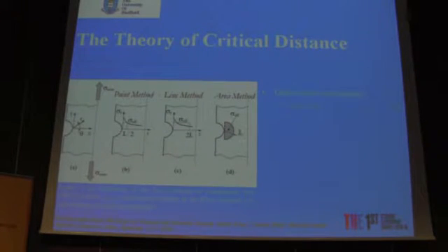It is well recognized that the theory of critical distance is the most effective tool which can be used by structural engineers to take into account the notch effect. If we pay attention to the model with static loading, we just use the simple linear elastic stress field to post-process all the data. This idea has been formalized in many different ways, such as the point method, the line method, the area method, and the volume method.